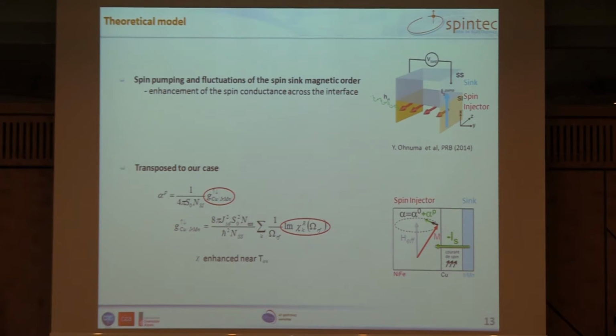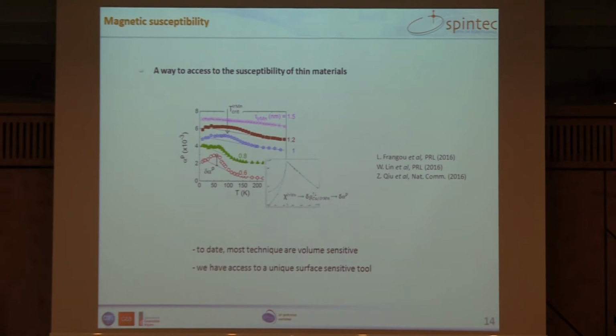There is some theory in the literature which deals with spin pumping and fluctuations of the magnetic order of the spin sink. This theory says that at the magnetic phase transition, when the order fluctuates, you should have an enhancement of the spin conductance across the interface. So it's probably what we see. Transposed to our case, our alpha P is related to the interfacial spin mixing conductance, which itself is related to the dynamical susceptibility of our spin sink. And it has been shown during the workshop, and demonstrated before, that the susceptibility of an antiferromagnetic material shows a maximum at the critical temperature. So what we observe here, we think, is simply a signature of the magnetic susceptibility of our material.